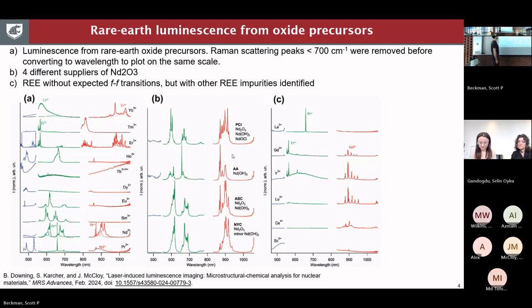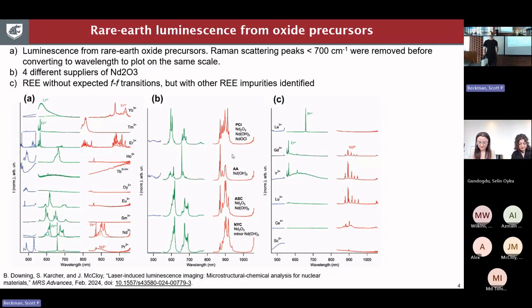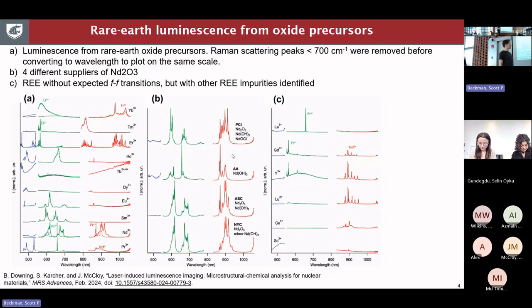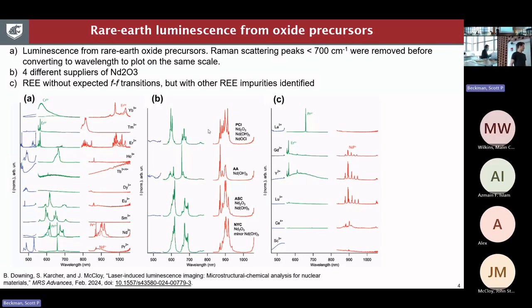In the middle, we have four different neodymium oxides. They are all three nines or higher purity according to the bottle, but they vary quite significantly in the luminescence spectra here, and there are also some minor phases which we identify using XRD. On the right, there are some elements which we don't expect to see luminescence in, but we still do anyway — and these are from contaminants that are not the primary rare earth.